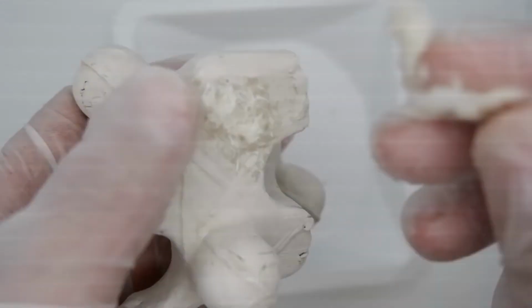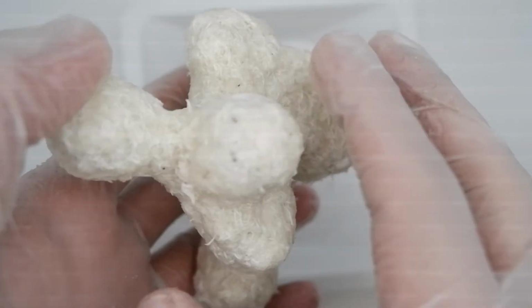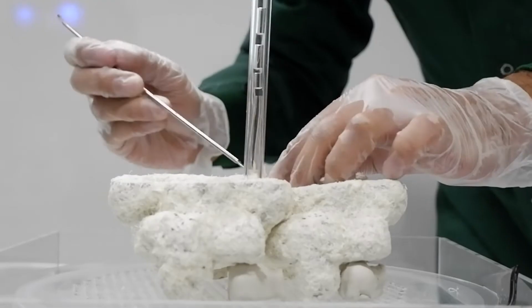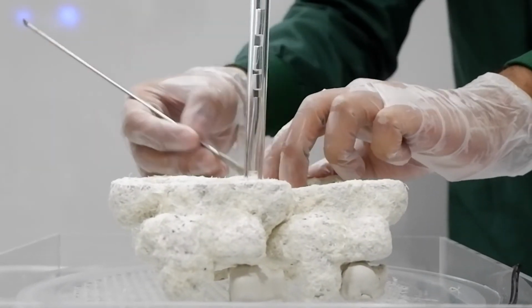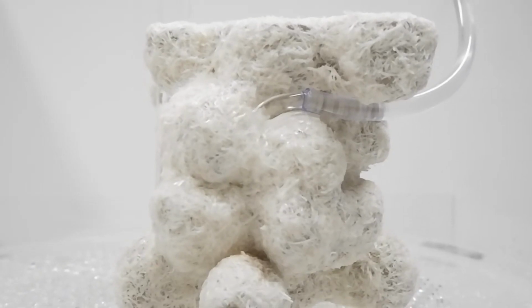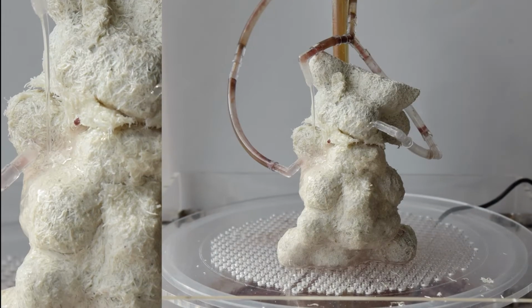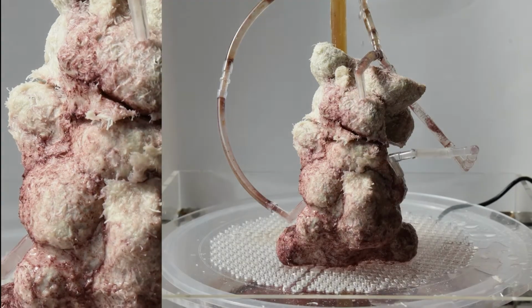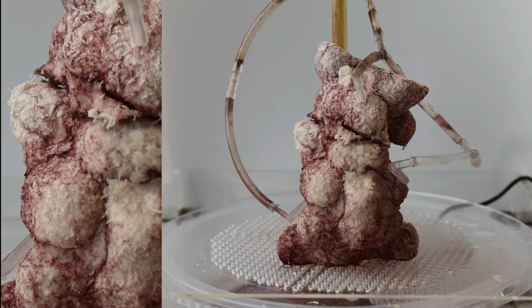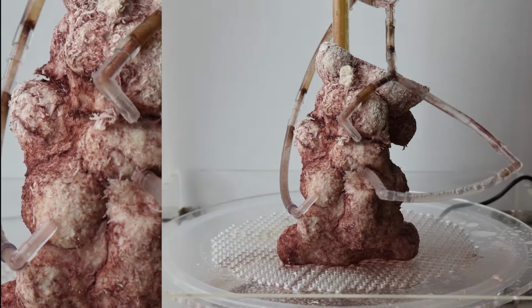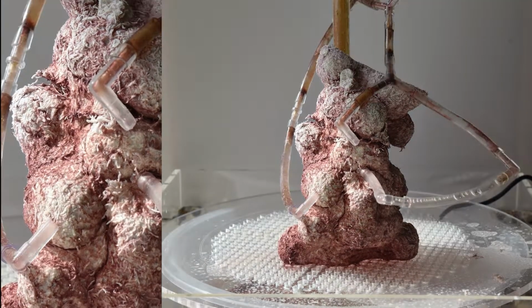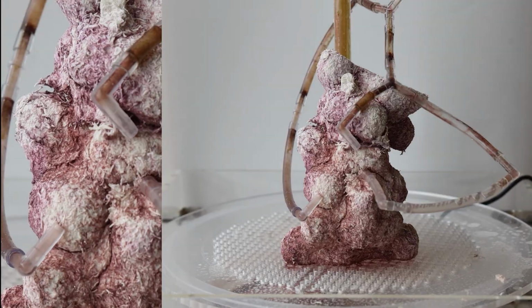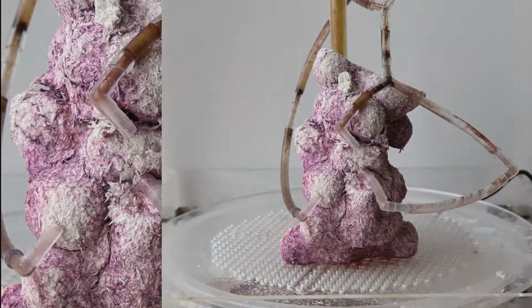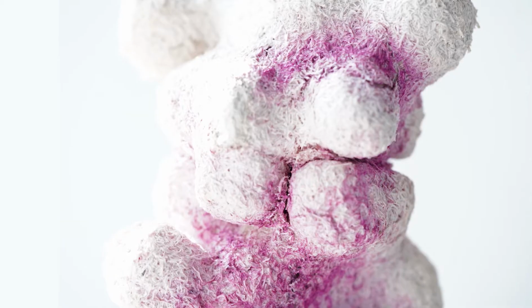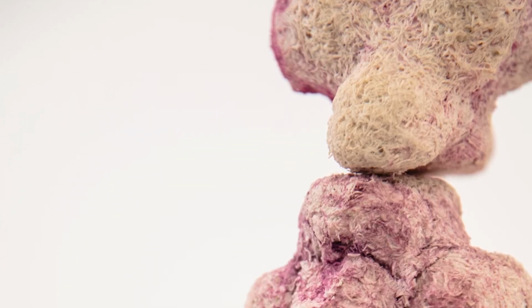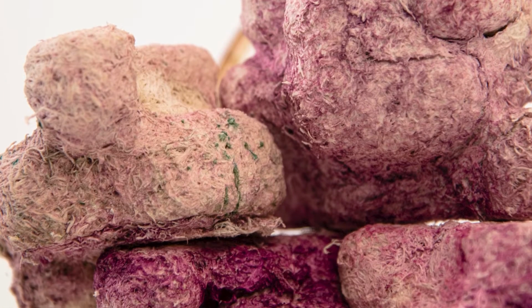A series of prototypes were plastered with the substrate material and glued together with the same material on cross-linking. Further, a red marine algae, Porphyridium purpureum, was upcycled with seawater for algal growth. The algae produces red biofilms that adhere to the substrate, while the substrate stays hydrated being a hydrogel composite. The phycoerythrin in the algae produces red pigmentation that on dehydration induces appealing hues of pink, ensuring biocoloration.